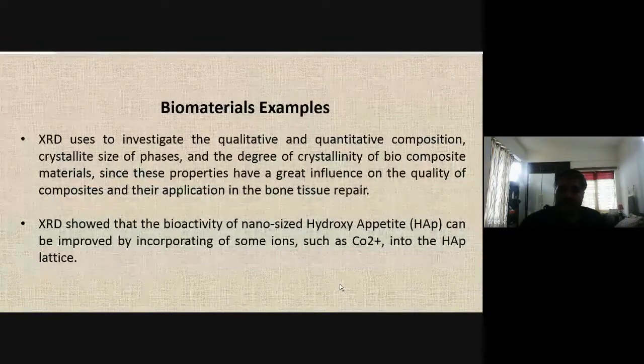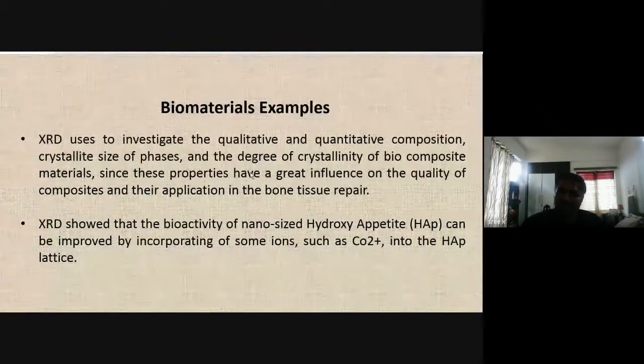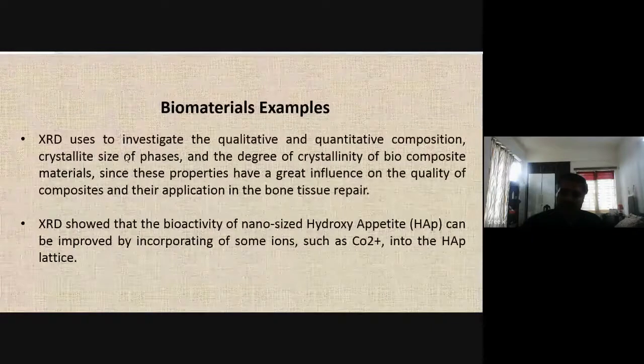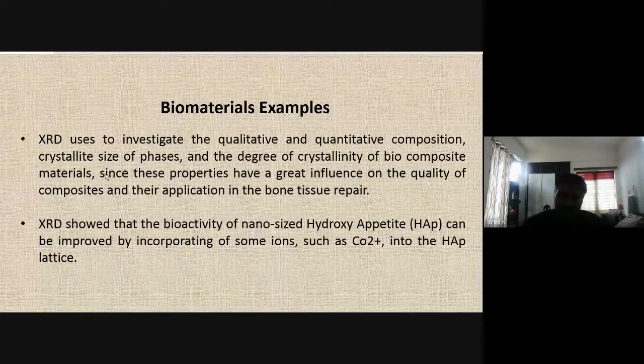Biomaterial example: XRD is used to investigate qualitative and quantitative composition, size of phases, and degree of crystallinity of biocomposite material. X-ray showed the bioactivity of nano-size hydroxyapatite, which can be improved by incorporation of some ions.